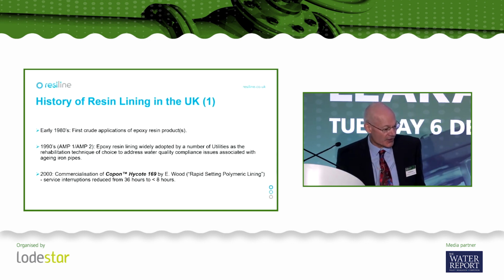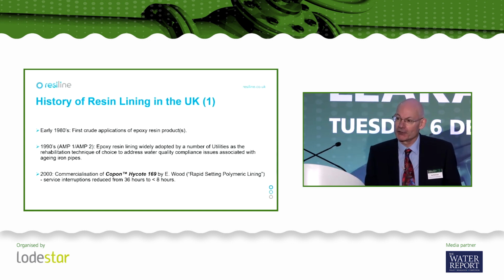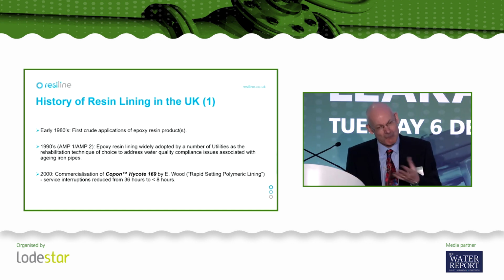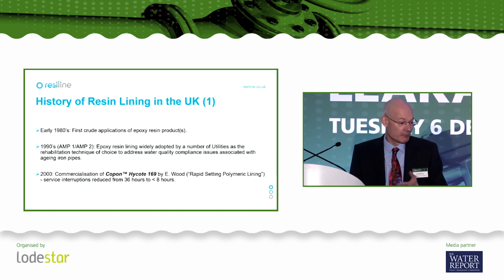Now, there was something of a seminal moment in the industry in 2000 when the E. Wood Company, based in Northallerton in North Yorkshire, launched the Hycote 169 product, which at the time was christened the rapid setting polymeric lining, which was actually a polyurea product utilising aliphatic polyisocyanates. And basically that material hardened in 2 minutes. So it meant that all of a sudden, all that dead time associated with the curing of epoxy resin had been eliminated. So it meant that mains could be rehabilitated and returned to service, all in the same day.